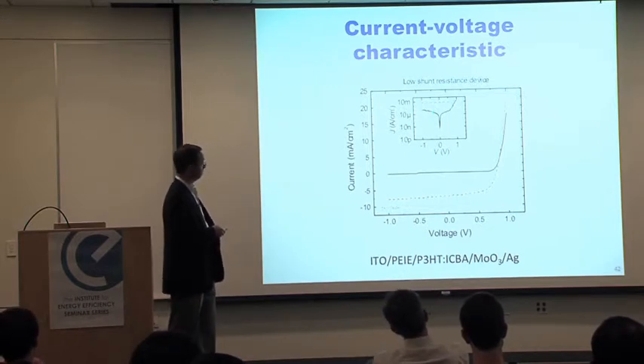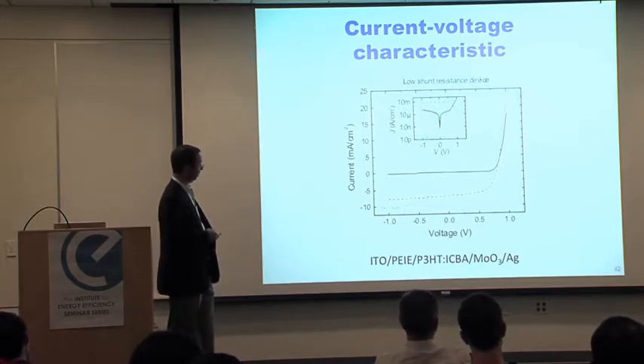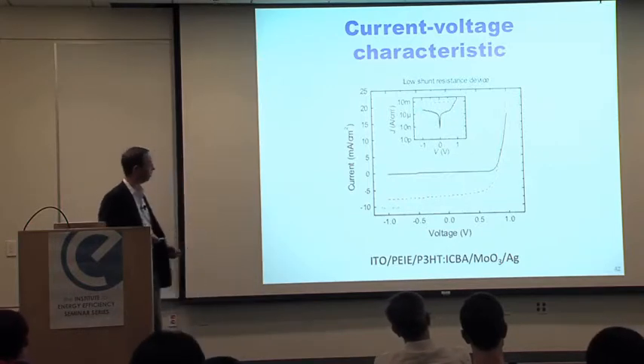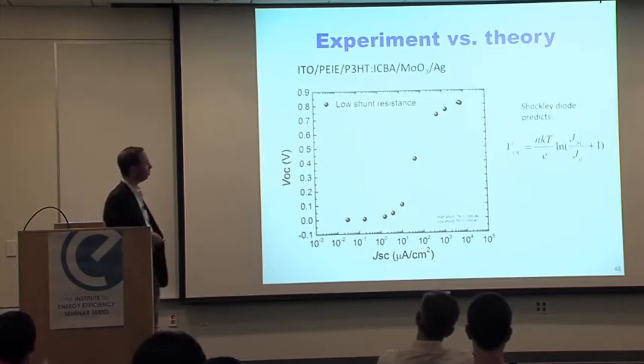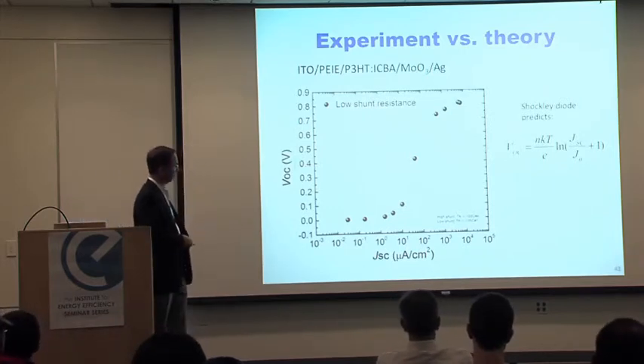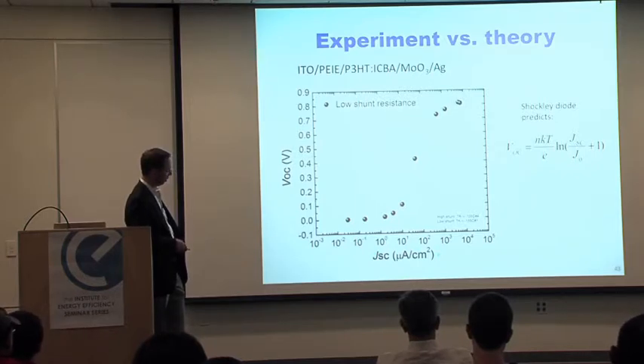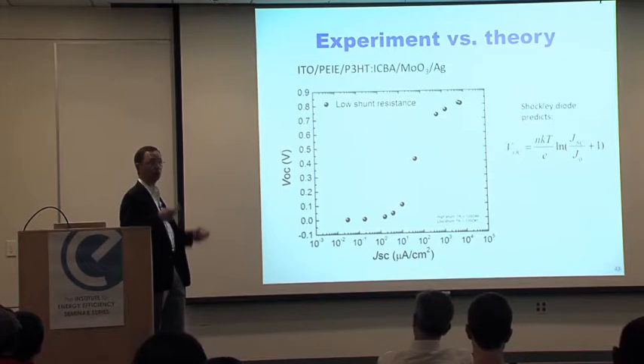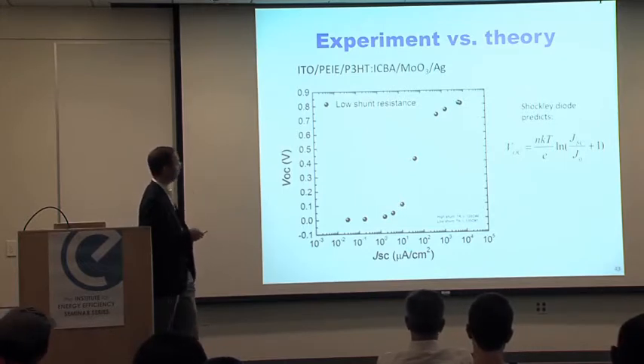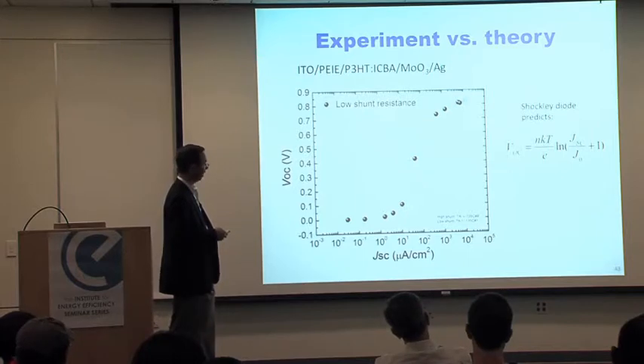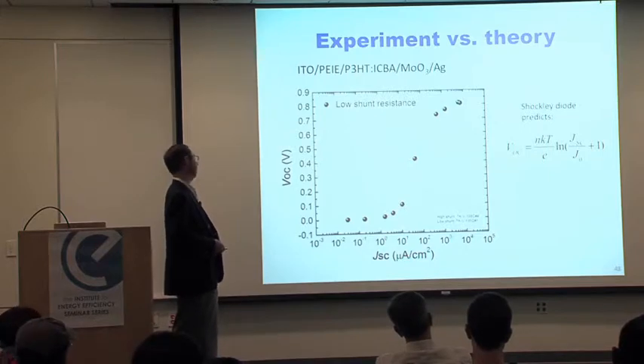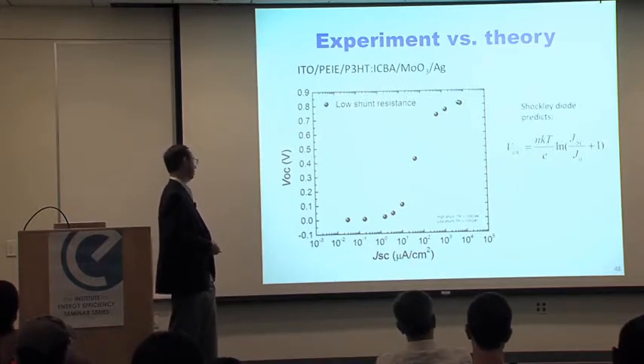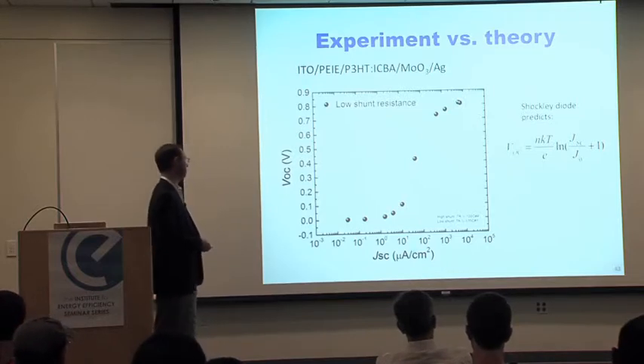So you see in that first device that if you measure the current level in reverse bias in the dark, you get currents here at -1 volt, which is of the order of 100 microamp per square centimeter. Okay? If you take a device like this and you measure the open circuit voltage as a function of the short circuit current, which here just scales with the illumination or the irradiance of the solar cell. So you start here at 1 sun, where you get about 10 milliamps, sorry, that's microamps, so yeah, 10 to the 4 microamps per square centimeter is about 10 milliamps per square centimeter.